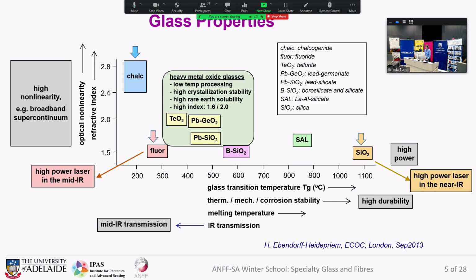In the middle, we have the heavy metal oxide glasses: tellurite, lead silicate, lead germanate. So they have a really interesting combination of glass properties like low temperature processing, high crystallization stability, high rare earth solubility, high index, and that really makes them suitable for easy processing. And so we use them a lot for creating, investigating new sensing and other concepts.